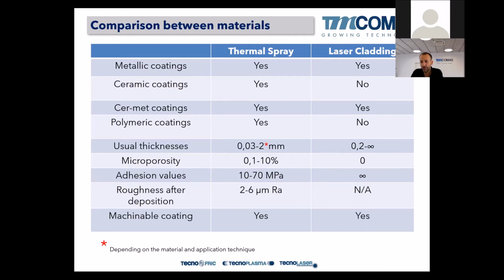In laser cladding it is virtually infinite, so there's no restriction in thickness, although it also depends on the feedstock material. In very hard materials like stellite or tungsten carbide or tool steels with a lot of chromium and carbon content, the hardness of the welded layer is very high. We cannot go very high in thickness, but generally speaking, with stainless steels, we can clad up to 10 millimeters or 20. But okay.